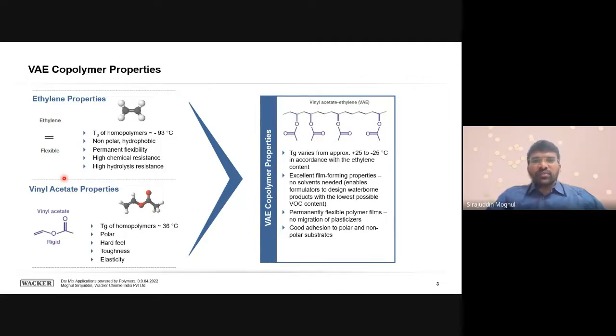Otherwise, when we use other chemistries, for example styrene acrylic chemistry, styrene and acrylic both are hard, and it can give flexibility only to a certain extent. So in order to enhance the flexibility of a styrene acrylic, we add some plasticizers. But with time, these plasticizers move onto the surface, because the usual tendency of a plasticizer is to migrate onto the surface, and then they evaporate. Once they evaporate from the surface, it becomes very rigid.